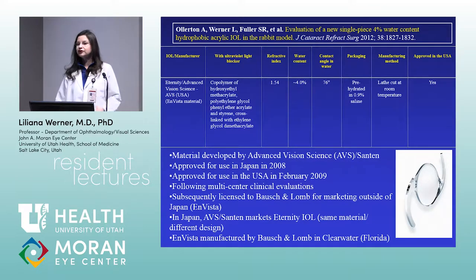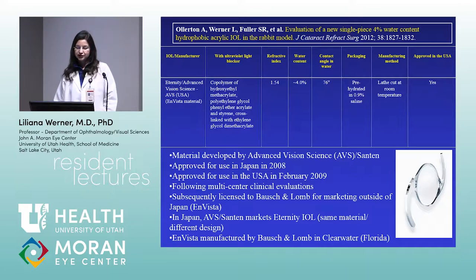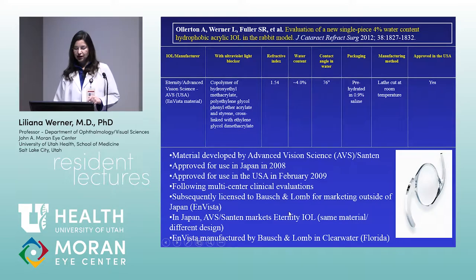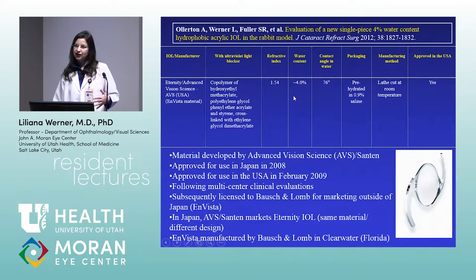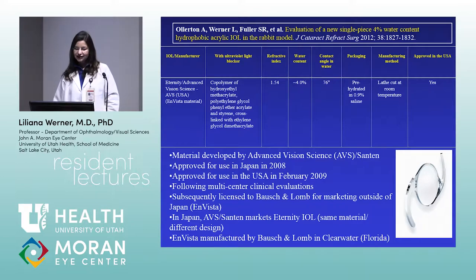There is a problem named glistenings in hydrophobic acrylic materials. There are new materials in the market — for example, one developed by AVS and licensed by Bausch and Lomb, used in the Eternity intraocular lens — a hydrophobic acrylic material with a water content of almost 4%. Such material prevents glistening formation. It is the only IOL the FDA has approved as glistening-free. In laboratory tests, we cannot induce glistenings with this material.